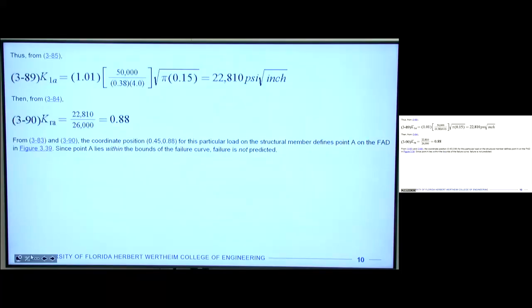Then we can go back and calculate our fracture toughness, K1A. It's C times our applied stress, sigma A. So it's 50,000 pounds divided by, and here they're just using the nominal area. You can use the nominal or you can subtract off the crack length. So that's an approximate stress, times the square root of pi times crack length over 2. And so we come out with a fracture toughness of 22.8 kpsi square root inches. Okay.